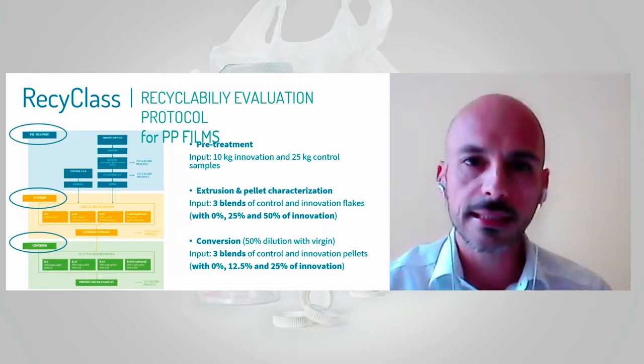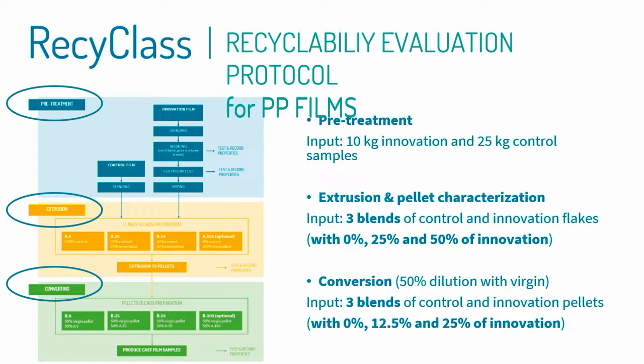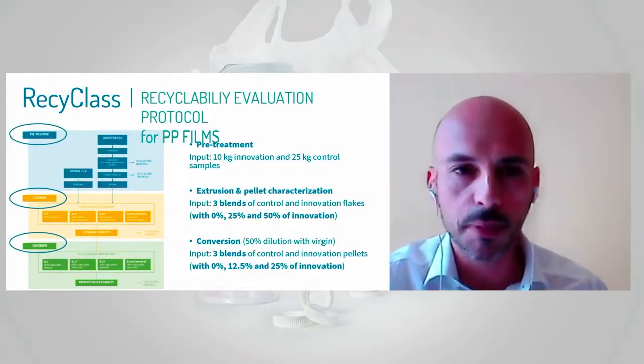This is also how the RecyClass recyclability evaluation protocol looks. We have a protocol fully dedicated to polypropylene films that is based on the best practice of the industrial recycling process for polypropylene flexibles. The protocol is based on three main steps: pre-treatment, where typically the material under analysis is ground, washed, and processed by density separation, the flotation. Then after drying, the material is blended with what we call a control film, which is a fully recyclable one, and with different concentrations of the innovation film, the material is extruded for a certain period of time, and then the pellets representing the recyclate are characterized and compared one by one, property by property, to check if the innovation film will determine any decrease in properties in the recyclate.